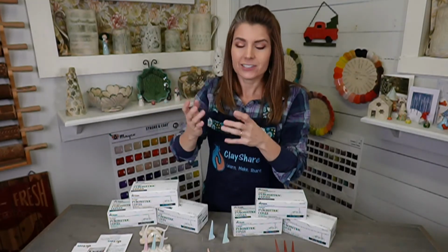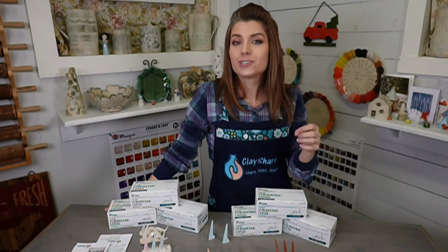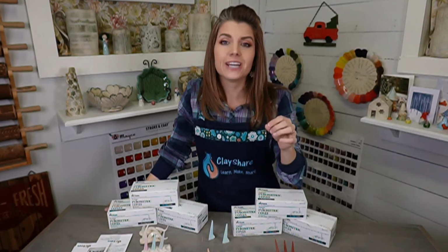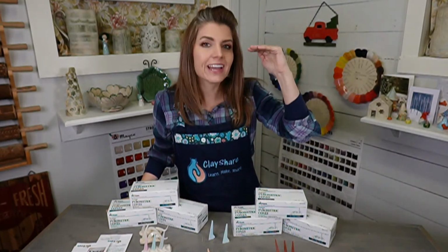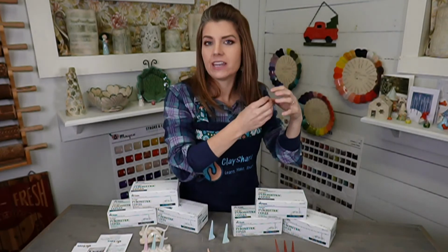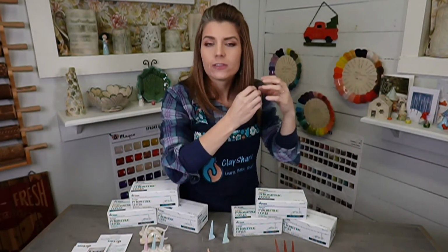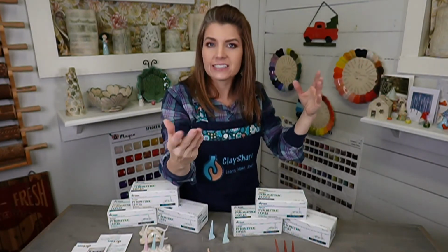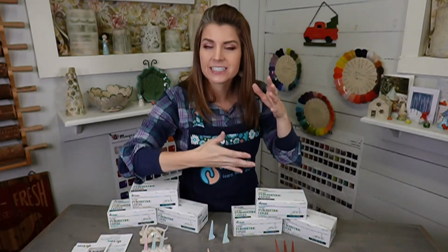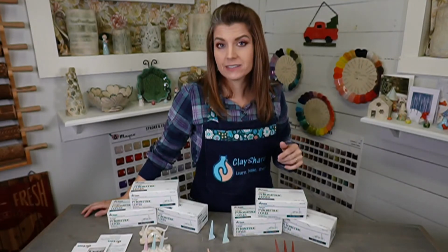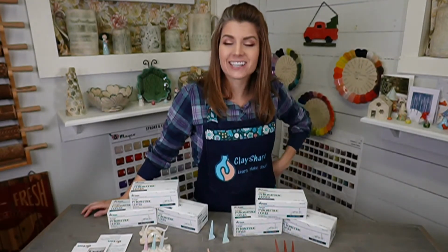It's melting. So yes, if you are struggling with pinholing, if you're struggling with uneven glazing, I suggest you add a hold to your firings, because what it will do is it will hold your piece right at that temperature. It allows the gases to come out, those bubbles to make their way out of your glaze, the glaze to melt fully and seal itself over the surface so you don't get those pinholes or those bumps. And that makes a huge difference in your firing and the quality of your pieces. So yeah, exactly right. Chris, caught on.